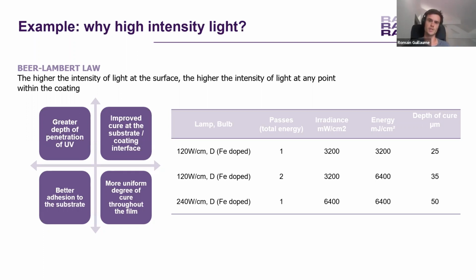And on the right, you can see an example of that. If we take the first line, a lamp of 120 watt per centimeter, we pass one time below it. The lamp has an irradiance of 3,200 milliwatt per square centimeter. Let's say that one passage through the lamp is equal to 1 second. So with 1 second of irradiance of 3,200 milliwatt per square centimeter, you reach a total energy of 3,200 millijoule per square centimeter. With this lamp, we measure a depth of cure of 25 micrometers.